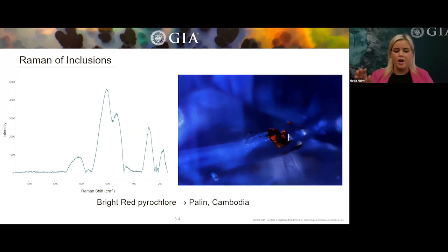So here's an example of using Raman for assistance in an origin call. So this nice bright red crystal was identified as pyrochlore, and when it's bright red like that, bright red pyrochlore is commonly found in blue sapphires from Cambodia. So it's identified. We have bright red pyrochlore. Our gemologist is probably going to be leaning towards Cambodia for the origin. Now, if it wasn't bright red, maybe it was orange, the gemologist might be leaning another direction for the origin of this stone.